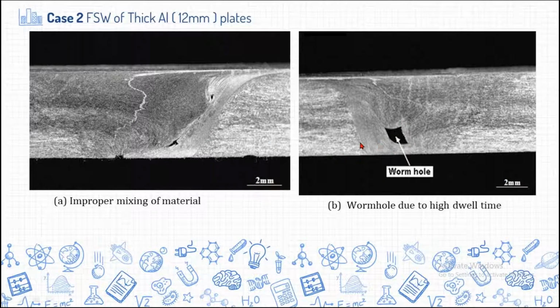defect. Many researchers also reported this kind of wormhole defect in the FSW process. The possibility is that high dwell time, more dwell time, is the reason for the wormhole defect over here.